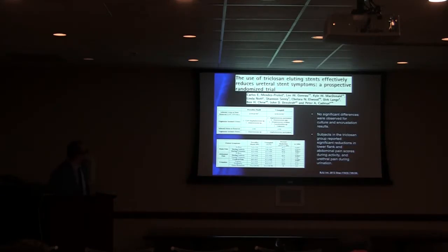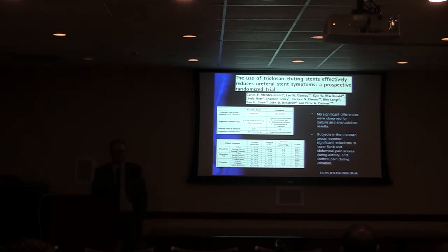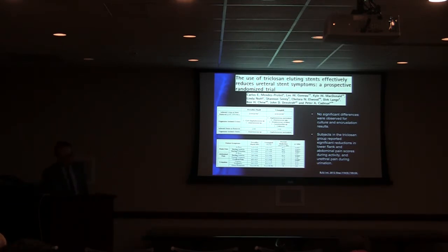Finally we're getting somewhere. And so now you move into humans. And it's a whole different ballgame. Because what we found in humans was that, unfortunately, there was no significant difference for culture and incrustation results. Okay. And again, you can see here. Now, admittedly, it was only done in 10 patients, but a small trial like this can even make or break a promising product. So anyway, you can clearly see that, again, no differences in terms of culture positives or incrustation results.